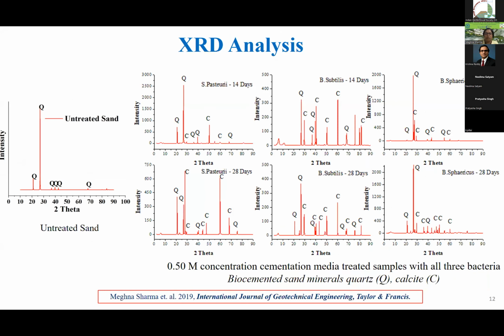Yeah, so after that, XRD analysis: through the XRD, untreated sand had only quartz peaks, so that means it was pure quartz sand. And in the Sporosarcina, in the subtilis, and in the sphaericus, every bacteria-augmented sample has the calcite precipitation peaks. So the calcite precipitation occurred in every bacteria combination, whether treated up to 14 days or 28 days, both.